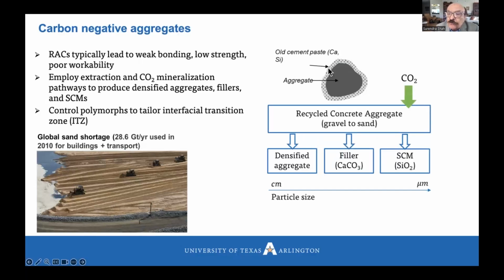And so we want to solidify this porous aggregate. So if you carbonate this, then you have calcium carbonate, and so that densifies the interface. And in fact, what is important, that very fine aggregate, when you recycle fine aggregate, it also produces supplementary cementitious material. So the advantage of carbonating recycled aggregate: no more quarrying sand or natural aggregate, and also you are capturing